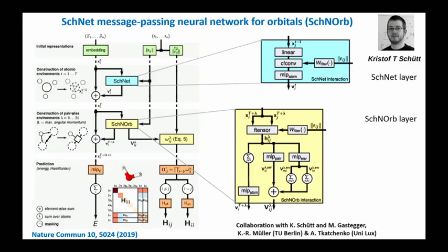So with most atomistic machine learning, we have atomic embeddings, and for each atom in the system, we have some type of feature that we're propagating through this whole network where there's lots of stuff happening. So for each atom, there's a feature X. And as in interatomic potentials, we have to train the model to understand the local environment of the atom and how that affects its local energy and local properties. And then at the end, the sum of these properties would be the energy. In addition, what we have to add here now is a way to create pairwise features. So we have to make some tensor contractions of atomic features, because of course in a Hamiltonian, I have interactions of orbitals within a block on that atom, but I also have interactions across atoms. So I need to have features that tell me about what's happening between atoms. And that's what's going on here. Then we construct a polynomial basis from these features, pairwise and otherwise, and we can construct the individual blocks of that Hamiltonian in that way. So that's basically what this says.